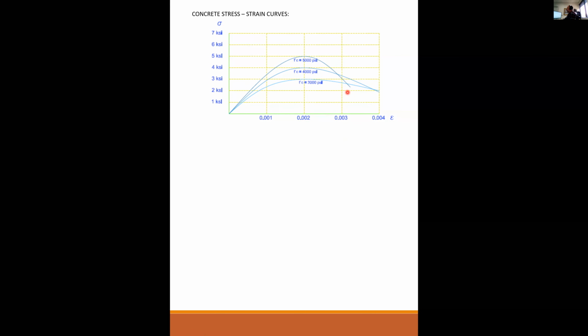So what's happening is the stronger the concrete is, the less strain it's able to sustain. It becomes more brittle, right? So the lower strength concrete is more malleable or ductile, if you will. The higher strength concrete becomes more and more brittle. And 6000, same trend. So on the stress strain graph, between 0 and roughly 40% of the strength of the concrete is acting basically elastically. So that means the stress strain curve is basically a straight line in this range from 0 to 40% of the strength of the concrete.